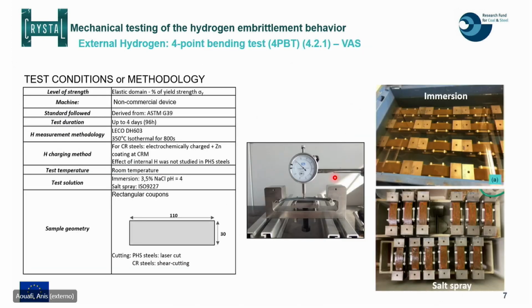The third and last result that I want to share with you is the result obtained when characterizing the external hydrogen effect. So the hydrogen comes from corrosion during the cycle life of the vehicle, and we use the same 4-point bending test that has been shared before in two different media, as I said before in the introduction: immersion in salt water with pH 4, or application of a cyclic corrosion test, the well-known salt spray test. Here are some photos to illustrate how the 4-point bending tests have been immersed in water or put in the cyclic corrosion chamber in order to follow the desired cycle.